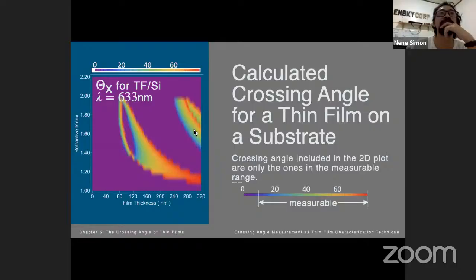So here is a two-dimensional plot of the crossing angle as a function of refractive index and film thickness at 633 nanometers. And I'd like to reiterate that our experimental setup has limitations. So the measurable range is only from 10 to 80 degrees. And that is why the crossing angle lower than 10 is not included in this plot since it's not measurable. So as you can notice here, these color bands represent the values of the crossing angle. And not every film thickness has a crossing angle.